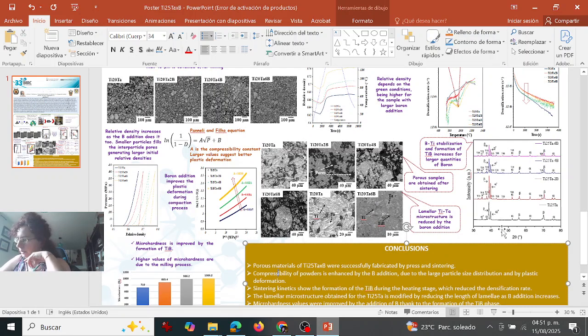If you have a look at these EDS graphs, energy dispersive spectroscopy, and analyzing the peaks, for example the alpha and the beta of titanium, we concluded that boron, titanium stabilization and formation of titanium boride increases for larger quantities of boron. So here we have the different percentages of boron for the samples. In here it was the sample with no boron, and in here we are increasing the quantity until we get to 6% of boron, and we've seen the different peaks.